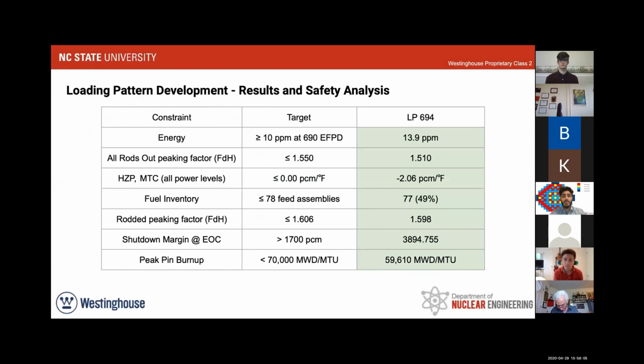Yes, so these are our results for both our limit as well as our safety analysis limits. As shown earlier, our energy requirement was met at 13.9 ppm concentration for boron at 690 effective full power days. Our ARO F delta H was also met. One thing that is good about the bullseye pattern type of core is that it is easier to get longer cycles out of that core. However, it is harder to meet peaking limits. So it was very good that we actually met these peaking limits with a good amount of margin as well.